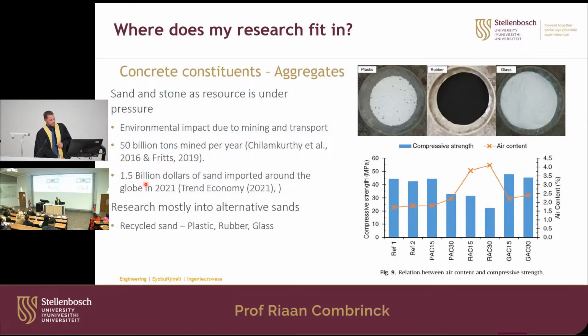So we've been doing research in alternative sands, especially things like plastic, rubber, and glass. So here's a picture of the plastic, rubber, and the glass. And you can see in terms of the compressive strength, if you add too much of the plastic, which is these two mixtures, the strength does decrease. If you add rubber, the strength decreases a lot. But glass does give you similar strength and often even higher strength. So there's some real potential in using that as alternative aggregates.